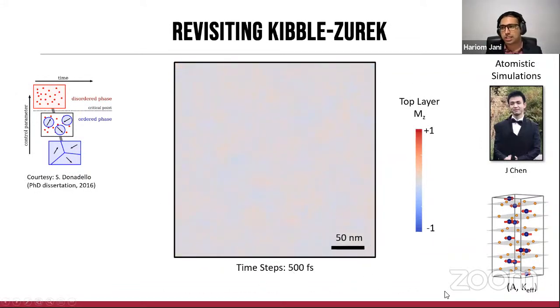Until ultimately all the textures annihilate completely and we remain in a purely in-plane oriented state, which is shown by the almost white color except for some very little noise seen in the system. So this is a very surprising result because it tells us that the topological textures that are created are actually undergoing annihilation when simulated purely by tuning the exchange and the anisotropy effects.